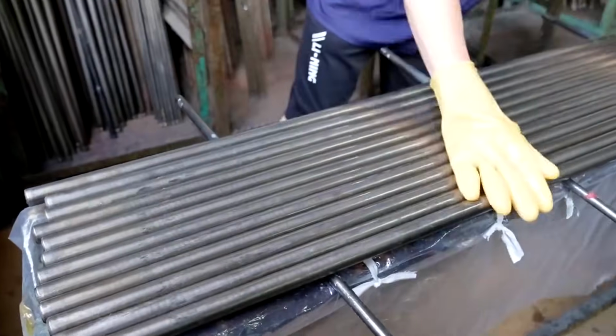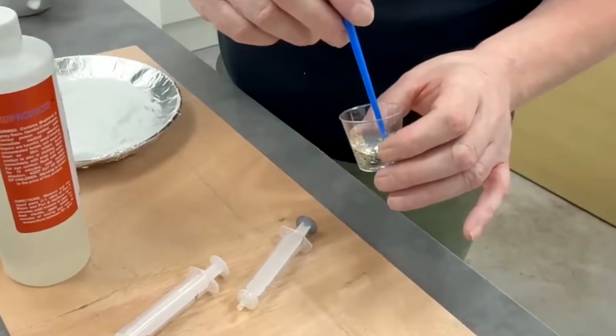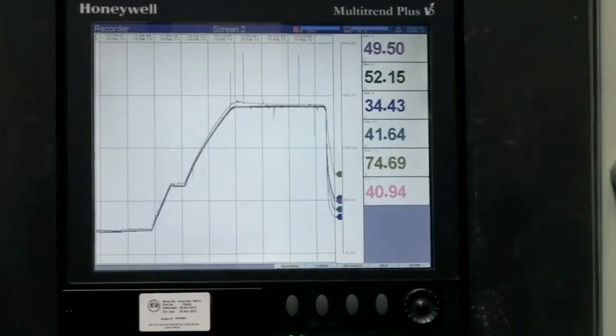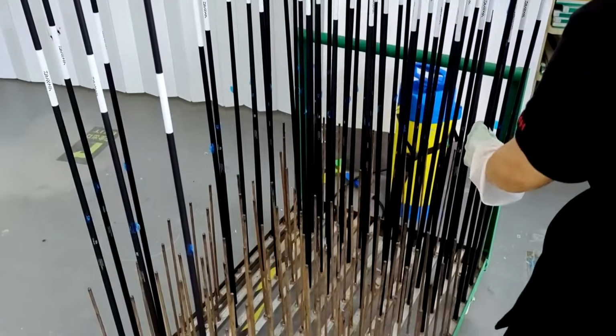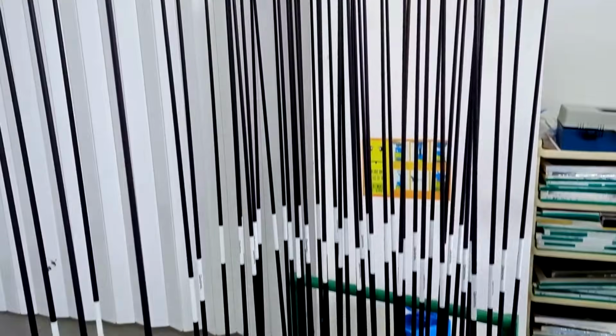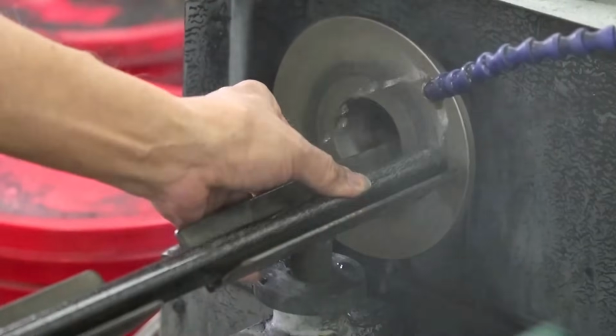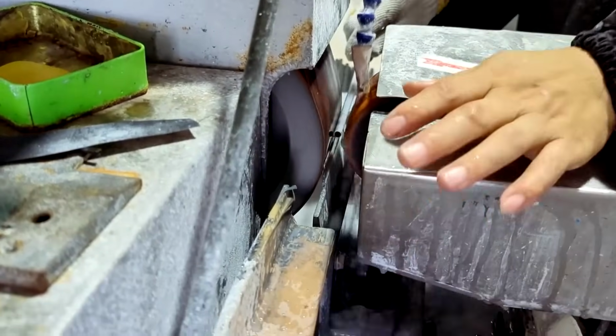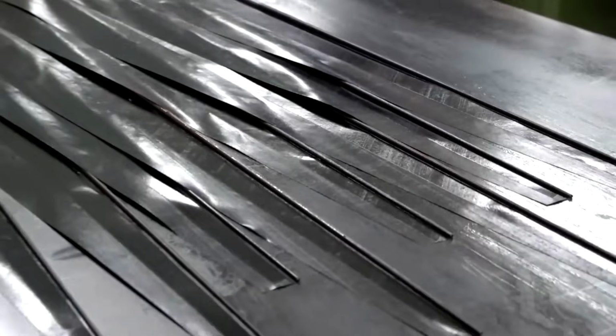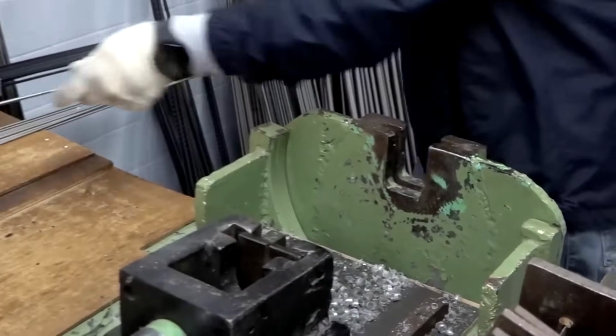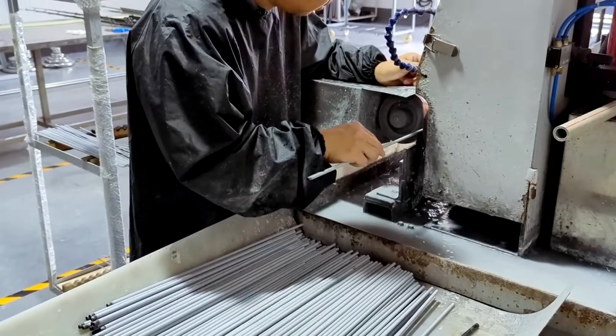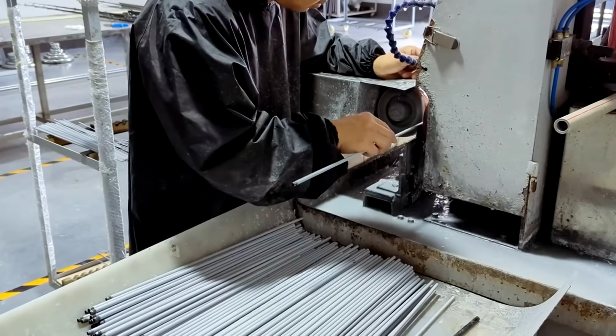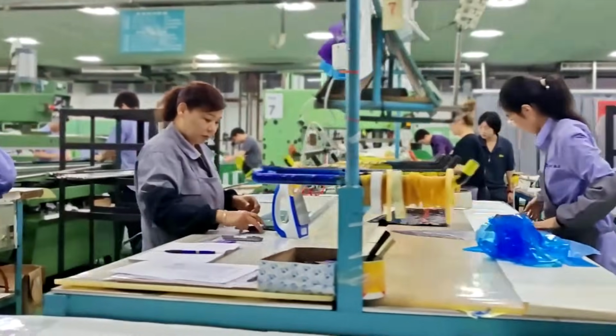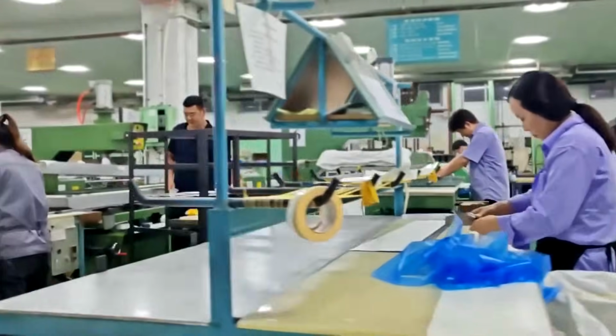284 degrees Fahrenheit is the standard temperature the curing oven reaches for this transformation. The mandrels, now secured with heat-resistant tape, are hung onto specialized racks and moved into the heated chamber. The heating cycle is monitored by computer systems to ensure the temperature rises evenly and remains stable without any fluctuations. This phase usually lasts for approximately 2 hours, providing enough time for the heat-reactive resin to fully activate and complete its chemical change. Inside the oven, the resin begins to flow, spreading between the carbon fiber layers and bonding them into a unified, nearly monolithic structure.